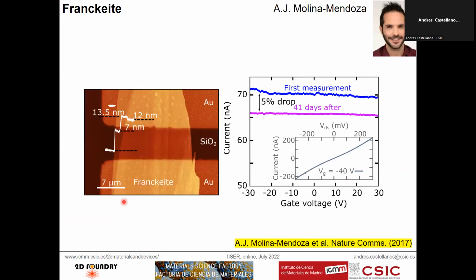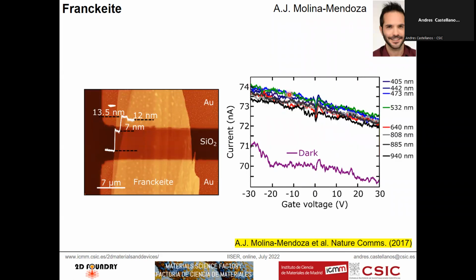And this is a flake of Franckeite, just a few unit cells. It is about 5 unit cells thick, 5 or 4. We transferred this flake in between two gold electrodes in order to fabricate a photodetector. And the device is rather stable. You measure the device, and after 40 days in air, you have just a small drop in the current. It's a P-type semiconducting material because the current decreases when you increase the gate voltage. And it reacts to light all the way to the near infrared. 940 nanometers was the longest wavelength we had back then when we studied this.